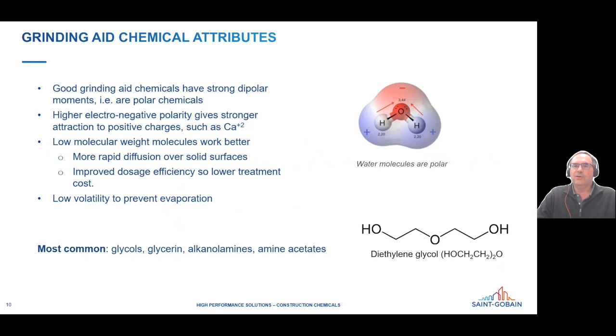And so if your grinding aid chemicals are evaporating quickly, then it's not going to be effective. So water molecules are shown here. Water is actually a pretty good grinding aid. I think the main drawback is that it evaporates in the mill. But at low temperatures, you can actually see a good effect from water.